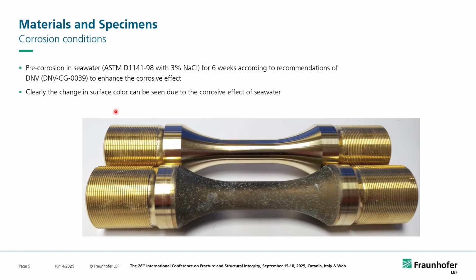And what we see at the end is here a sound specimen, so to speak, without any pre-corrosion, and then a matured and pre-corroded specimen. During the pre-corrosion, we kept those threads and also those sealing areas clean, and we covered them so that we at the end had only the corrosion effect in the mid of the specimen. And here we see a dark color, the surface turns a bit darker. That's a typical surface for those materials in seawater.